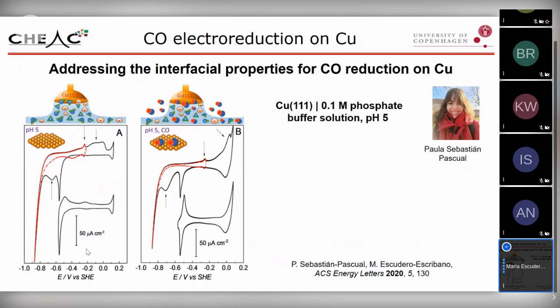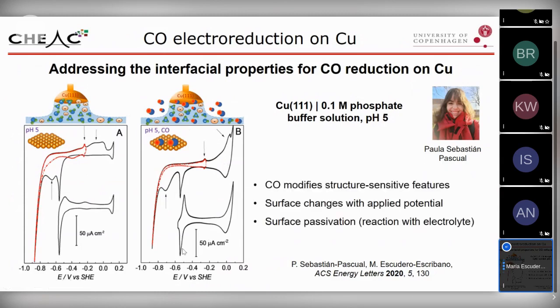Paula has been doing these experiments in phosphate buffer solution at different pHs, and this is just an example at pH 5. These are the cyclic voltammograms of this solution without CO, and this is in the presence of CO. There are a few things that we can see from these results. First, in the presence of CO, we see clear differences in the structure sensitive features. So CO is modifying the structure of the interface. There are surface changes with applied potential.